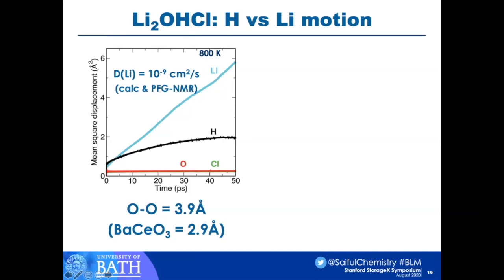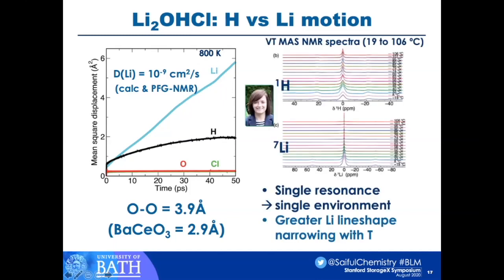Well, if you look at the structure of this anti-perovskite, it's very different from a classical oxide perovskite. The O-O separation is now 3.9 angstroms versus typically 2.9 angstroms in barium cerate or barium zirconate. And this was backed up by NMR. This was carried out by Karen Johnston's group up at Durham, and she performed some really elegant NMR work. I'm just summarizing some of her work. I'm not an expert on NMR.